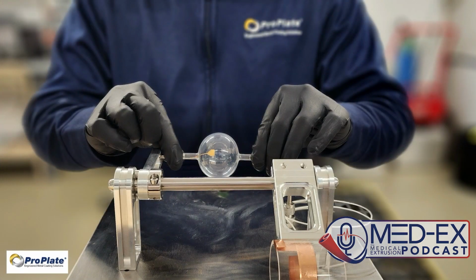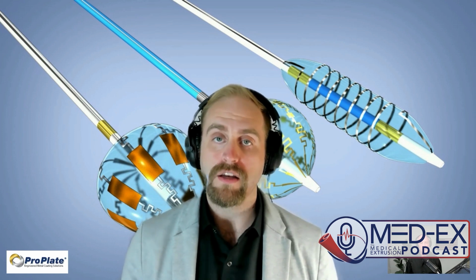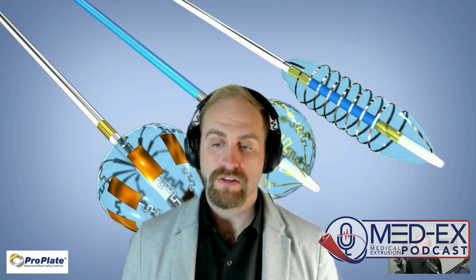Yes. So we've had to create some new test methods, but there are some ASTM standards out there that we use too. There's an ASTM tape peel adhesion test, which is similar to an electroplated metal and metal bond, where you take pressure sensitive tape and you press it onto the deposited area, you pull it off at a 90-degree angle, and you look for any signs of delamination. So that's a good test for tensile strength of the adhesion.